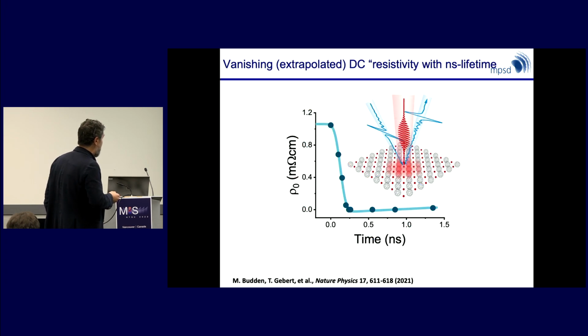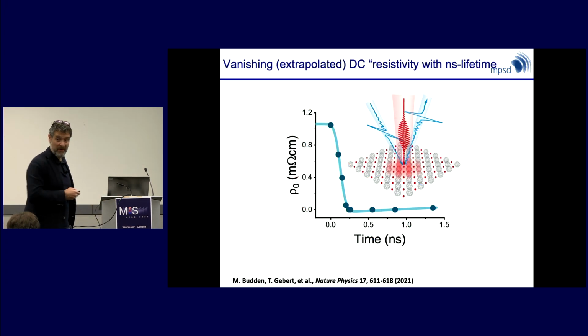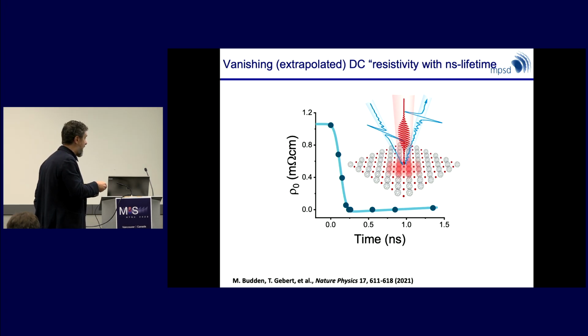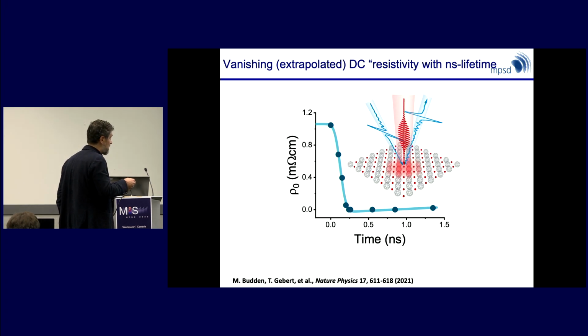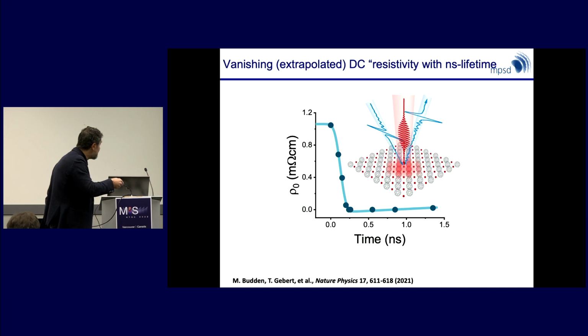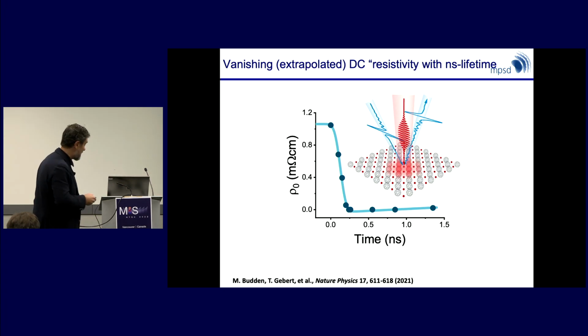So now this is my rho 0 that I told you about before. You remember I had a rho 0 that in the first experiments would go down in 1 picosecond and come back in 2. Now in these new experiments, you can fit the data, and you can extract this rho 0 that stays close to 0 for, let's say, more than a nanosecond. Now we can negotiate on exactly what defines the relaxation time. But let's say this is sort of a metastable state with very low resistance.